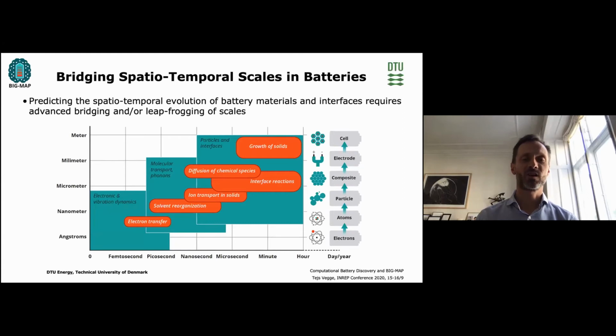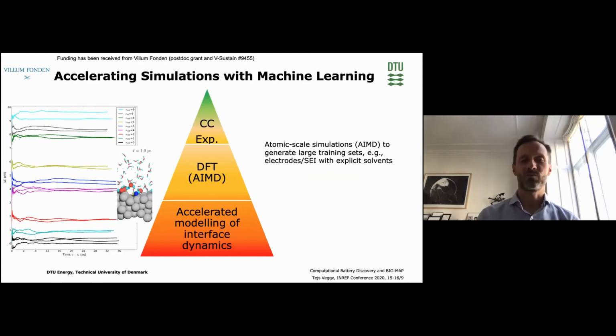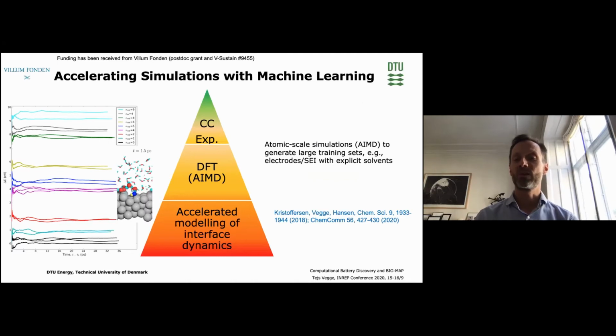And again, I'll start with the simulations as an example. So what you see here is ab initio MD simulations. So this is more or less state of the art of what we can do to describe solid liquid interfaces. And what we see here in work done by Henrik Kristoffersen and colleagues is that the inclusion of an explicit description of the electrolyte actually changes the property of the adsorbed species on the surface of the electrode.